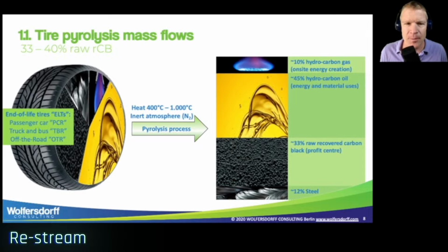So how is recovered carbon black produced? It's produced by pyrolysis, which is a depolymerization at heat between 400 and 1000 degrees Celsius in an inert atmosphere. Many companies are using nitrogen, some companies are using steam. And we're producing about 10% of a hydrocarbon gas, which is used for the on-site energy creation. We get about 45% of a hydrocarbon oil, which can be sold as a combustible or even in material valorization applications. And we get about 33% recovered carbon black. This is the profit center. And of course, this is the topic of this presentation. If you use whole tires, we also get 12% steel, which can be sold in the recycled steel markets.